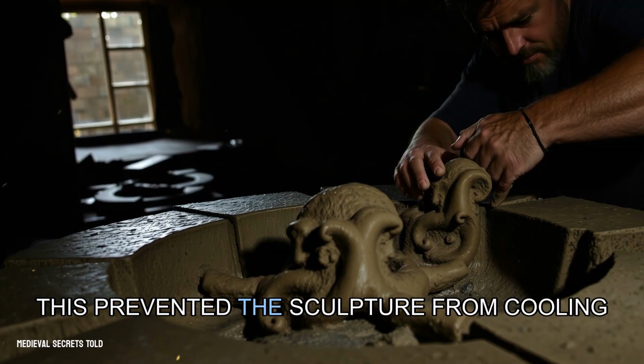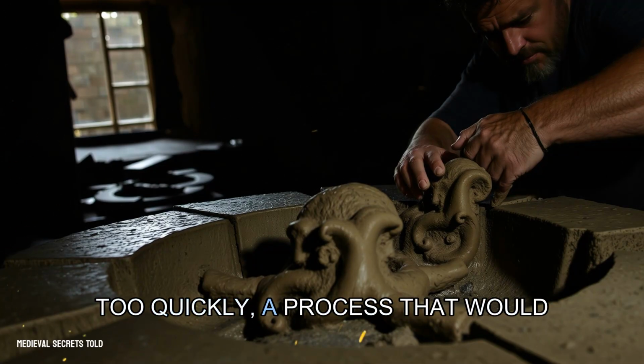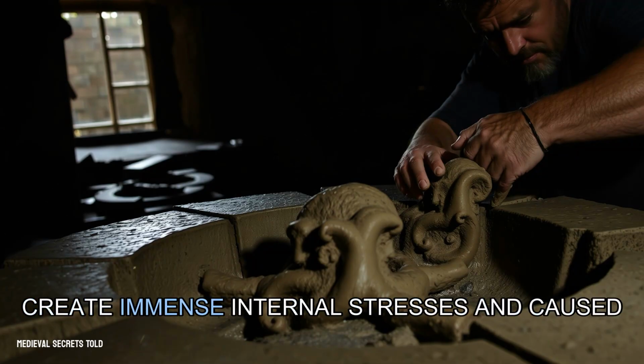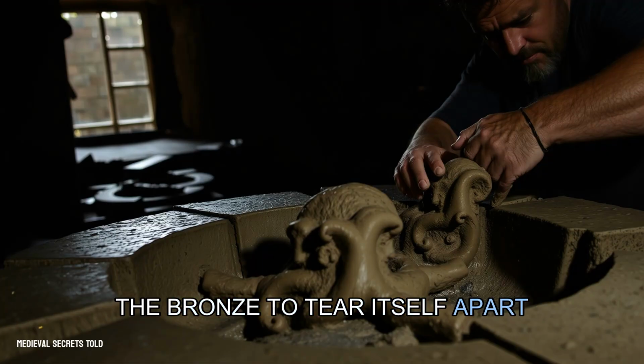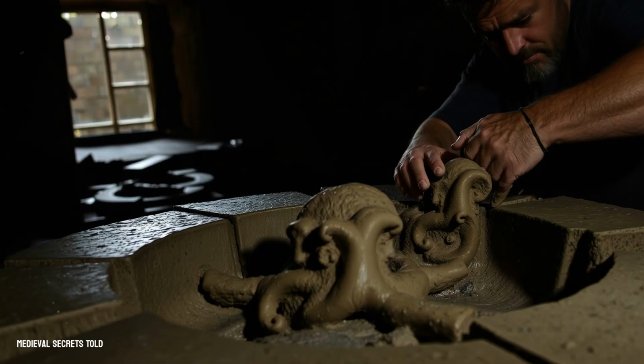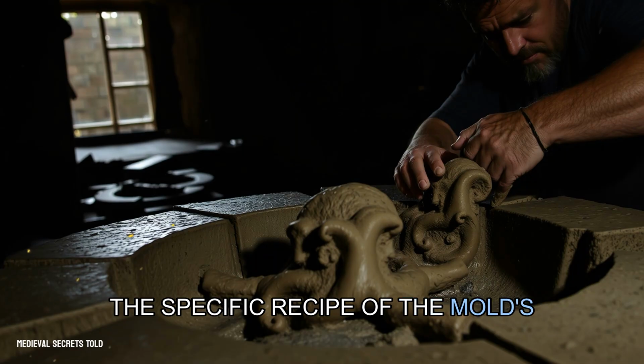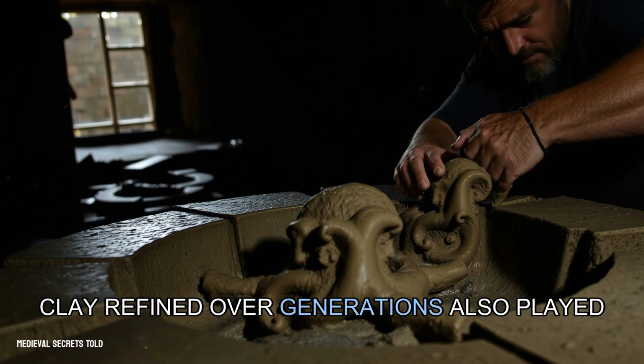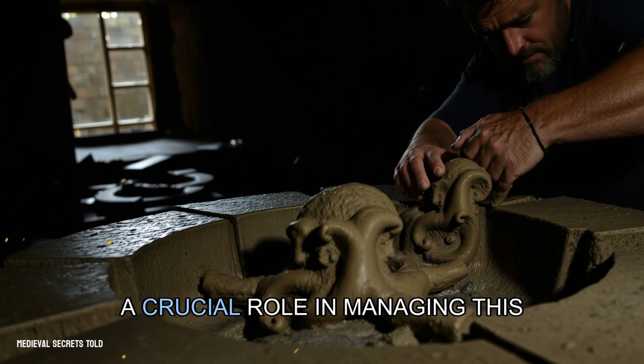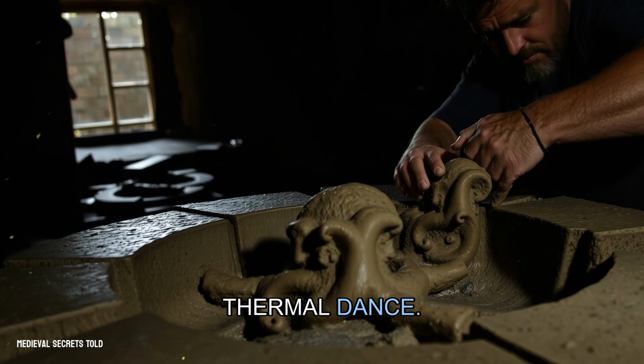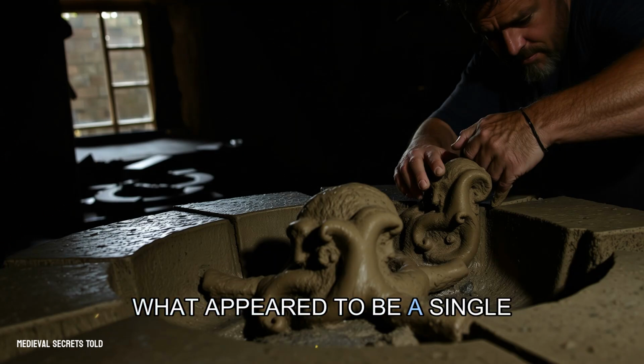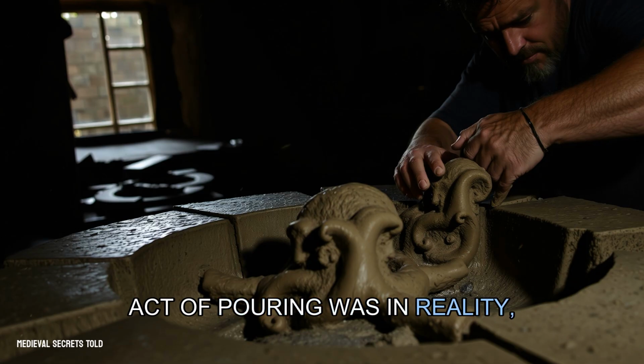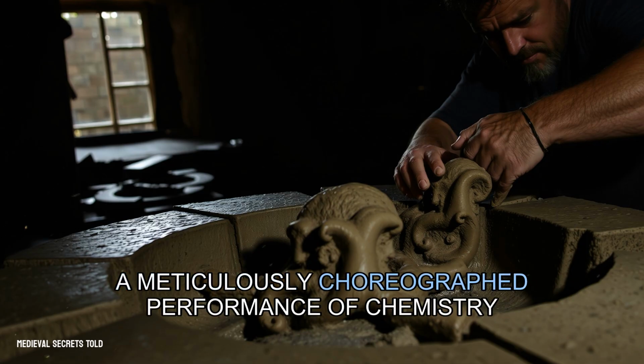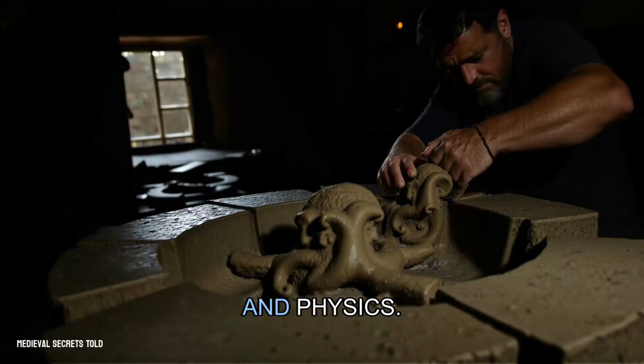This prevented the sculpture from cooling too quickly, a process that would create immense internal stresses and cause the bronze to tear itself apart with catastrophic cracks. The specific recipe of the mold's clay, refined over generations, also played a crucial role in managing this thermal dance. What appeared to be a single act of pouring was in reality a meticulously choreographed performance of chemistry and physics.